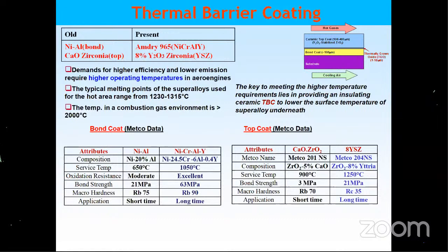There are two kinds of coatings. It has been done like this. First, this is the substrate material. Then this is the bond coat, and on the bond coat we have the ceramic coating. The bond coat is normally nickel aluminide or a combination of many metals, and the ceramic coat is based on zirconia. There are two kinds of zirconia available: one is calcia stabilized and one is yttria stabilized. Both prevent the material from being heated up by the hot gases. Normally in our engine we get about a 50 to 100 degree margin. That is very good, and the comparison has been given.